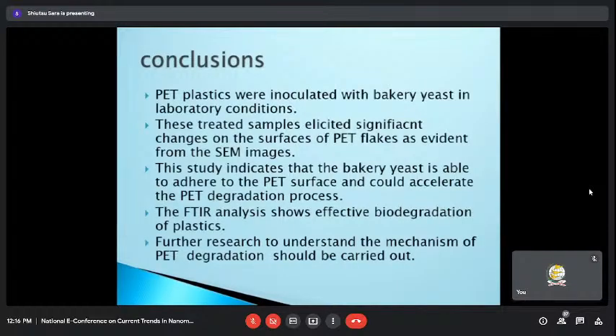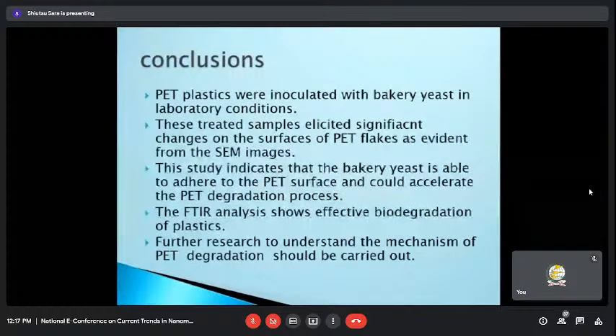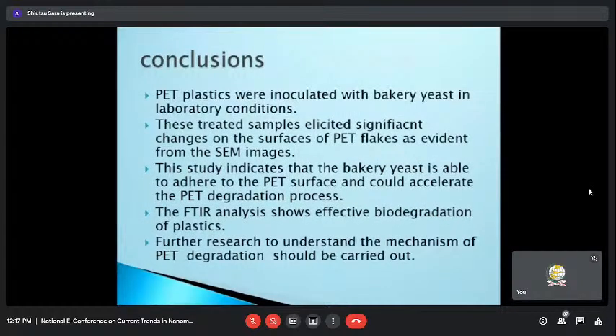So in conclusion, I'll just sum up the whole thing. In the first place, this PET plastic was collected and treated with a bakery yeast under laboratory conditions. After treating, it was kept in the laboratory condition for 1 month, and after 1 month, it was sent for FTIR and SEM analysis. From the SEM analysis, we have found some changes occurring on the surface of the treated samples, and from the FTIR, we have also seen the appearance of new peaks, indicating that biodegradation of plastics has been taking place.